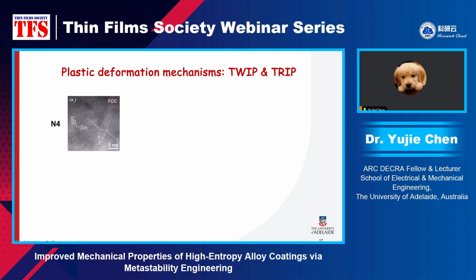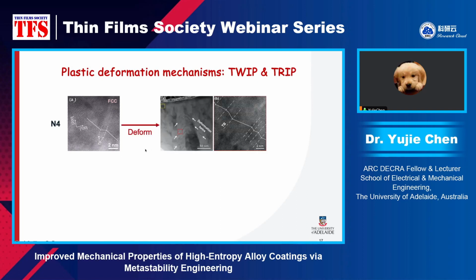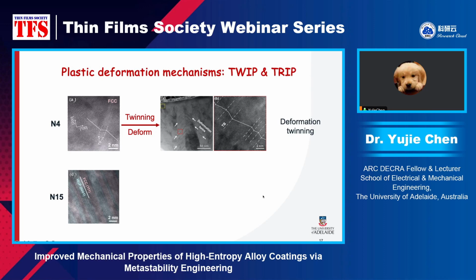So for the FCC structure sample N4 with a relatively low nitrogen content, we see that after deformation, extensive deformation twins were observed in the deformed sample, right? As can be seen in both low mag and atomic scale STEM image. So that means the deformation twinning happens during the deformation. And for another sample, N15, the dual phase one, the highly deformed region show a predominant HCP phase. So from a dual phase to a single phase, that means all the FCC phase has gone. So that indicates the FCC phase has transformed to HCP during deformation.